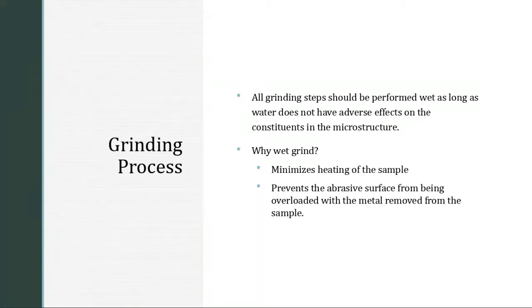So you want to minimize that heat, but you don't want to drown your sample in water during this process, because you do need some contact with the abrasive on the sample. Too much water, and your sample will hydroplane, just the way you would if you were driving 70 on the freeway and hit a puddle of water. You hydroplane, and since you don't have contact with the surface, you actually round out your edges, defeating the purpose of having any edge retention on your sample.